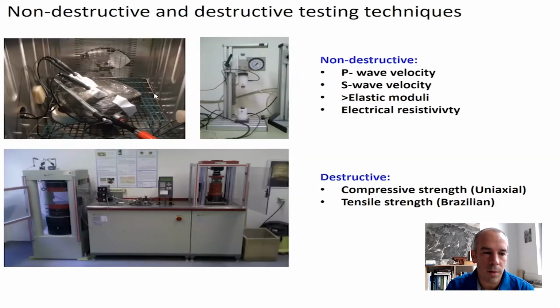To find out how rocks mechanically change upon thawing, we use non-destructive techniques. So we look at the P-wave velocities in this sample and how they change upon freezing. And we also like to use very destructive techniques. This is a hydraulic instrument that can do 40 tons on a sample. With this, we can crack unfrozen and frozen samples and compare how they perform. The same we can do with tensile strength, and this is then called a Brazilian test.